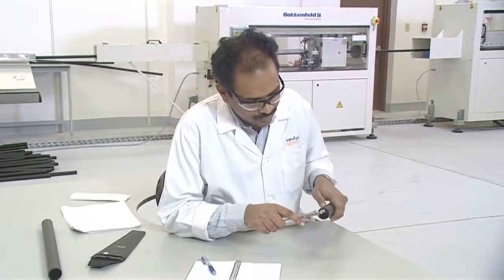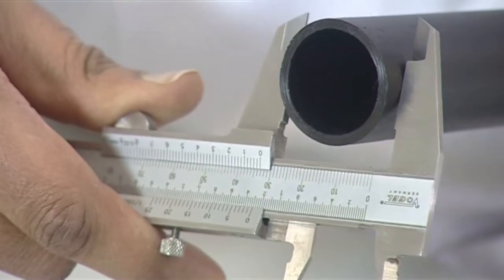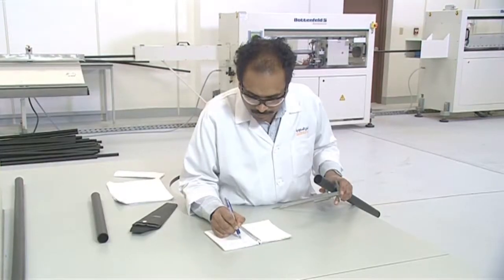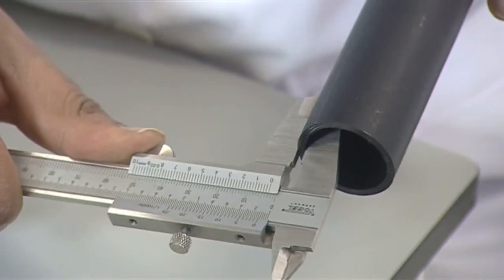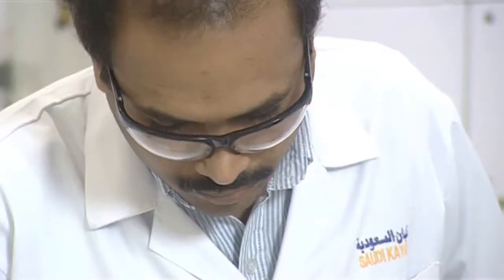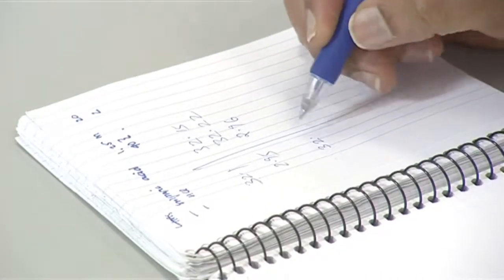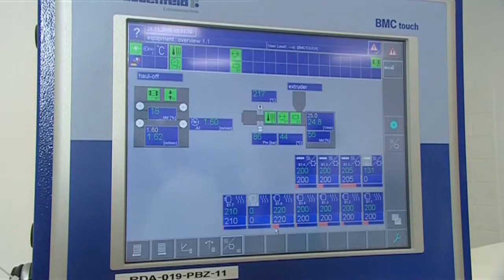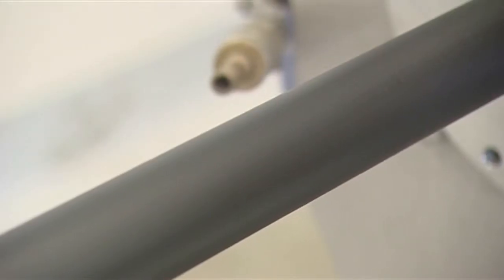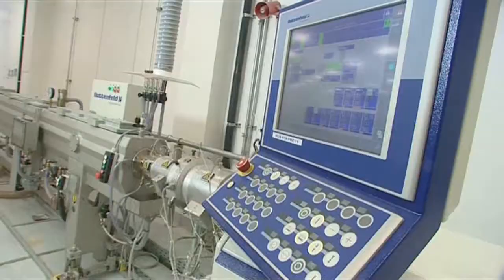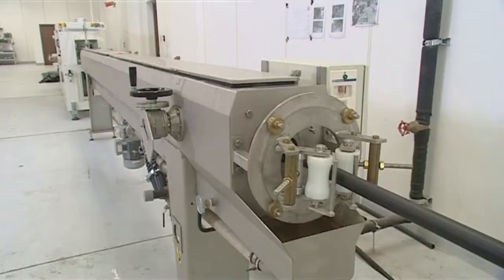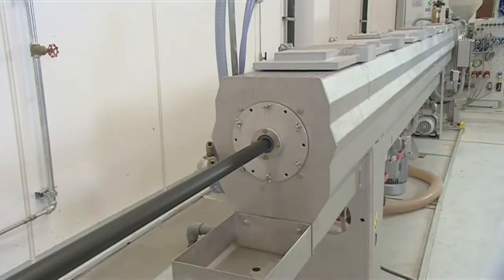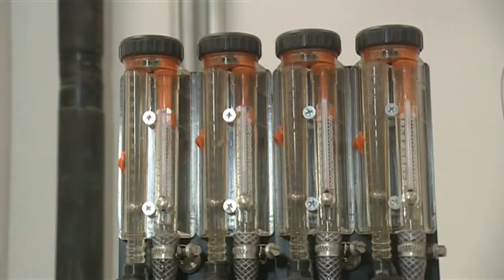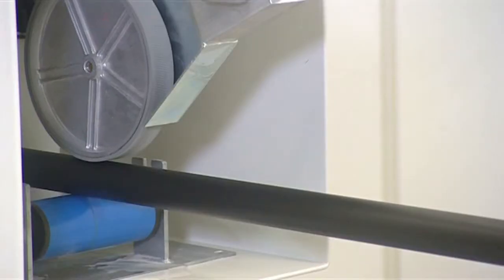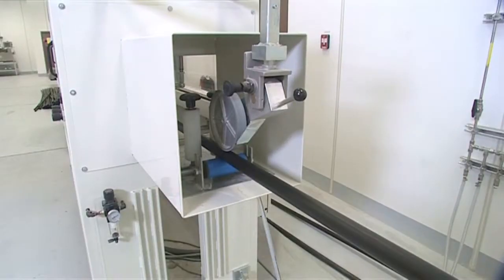As per international standards, dimensions of pipe are a critical requirement. The pipe produced is tested keenly for the dimensions and the appearance. To control the diameter and thickness, the pipe is passed through the calibrated die. Further, it is cooled under vacuum with water spray to maintain the shape. The pipe produced is cut automatically into required lengths.